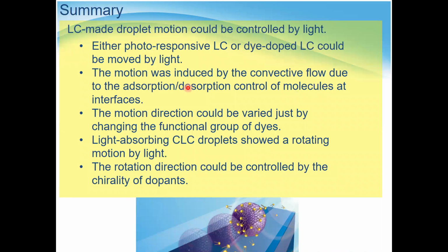So with this, let me summarize my talk. We demonstrated the photoresponsive liquid crystal droplet motion controlled by light, and the motion was induced by the convective flow due to the control of the molecules absorbed or dissolved from the surface or interfaces, and the motion direction could be controlled by just a minor change of the light-absorbing molecule.